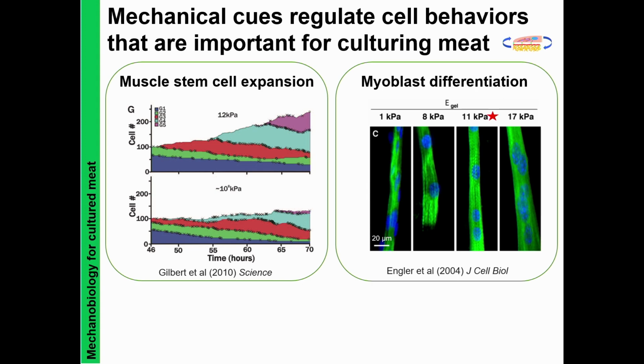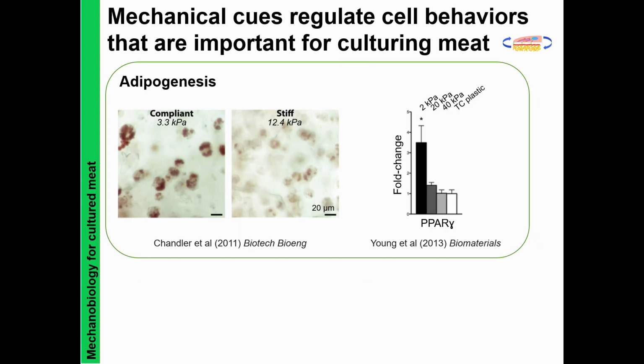We've also learned a lot about the importance of fat and adipose tissue engineering. And on this front, as Stephanie also mentioned yesterday, we know that the stiffness of the surrounding matrix can drive adipogenesis. In this paper here, we see that there's higher lipid accumulation for 3T3-L1 cells embedded in alginate hydrogels that are more compliant compared to the stiffer gels. And similarly, you can see increased expression of PPAR gamma, an adipogenic marker, for adipose-derived stem cells on softer rather than stiffer substrates. Again, supporting that the more compliant, softer matrices are important for driving adipogenesis.